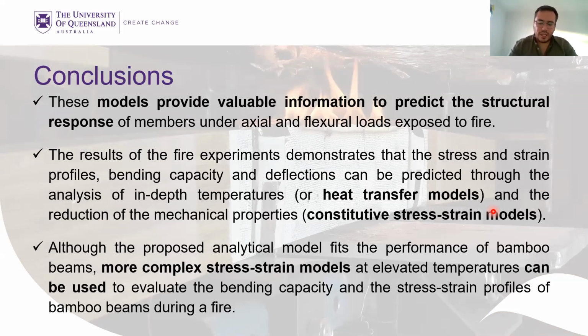So again, for the heat transfer models, we just use experimental results measuring the in-depth temperatures, but as many of you know, some other PhD students are working on numerical heat transfer models, which in the future will help us to predict those in-depth temperatures. So yes, we use a quite simplistic analysis for the development of those stress strain models. You can use more complex analyses like trilinear models or even polynomial models, but this approach was enough to get very close to the results.